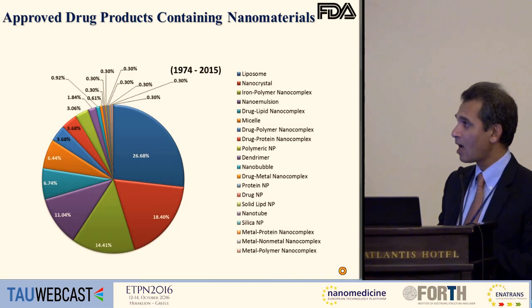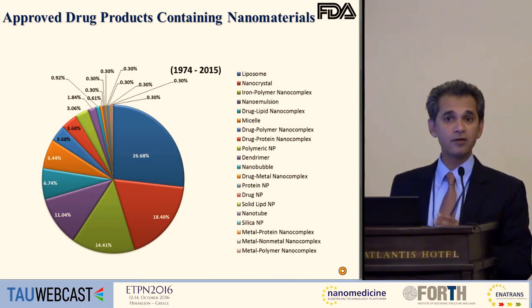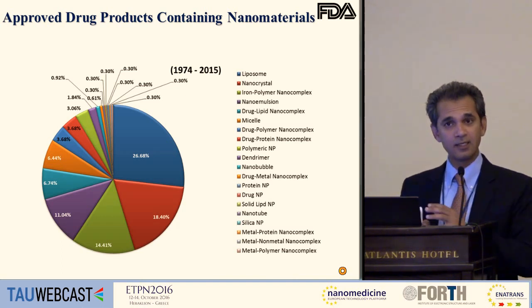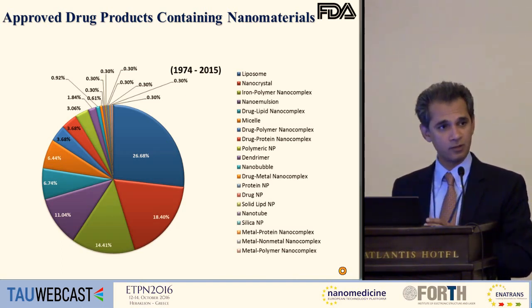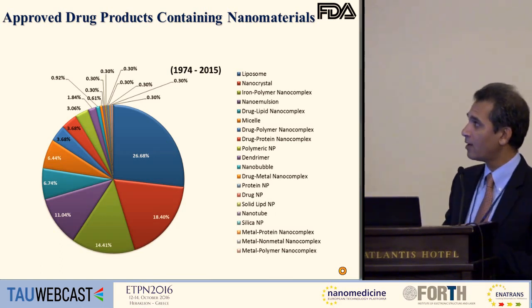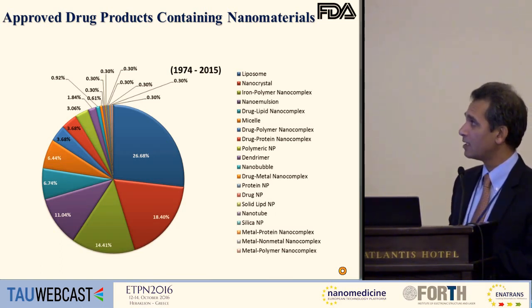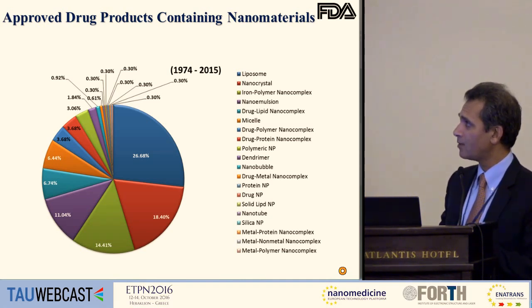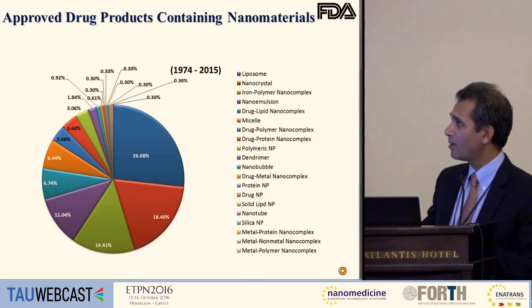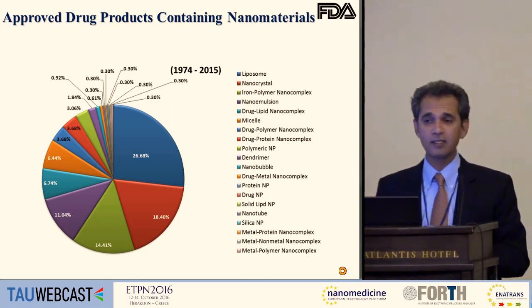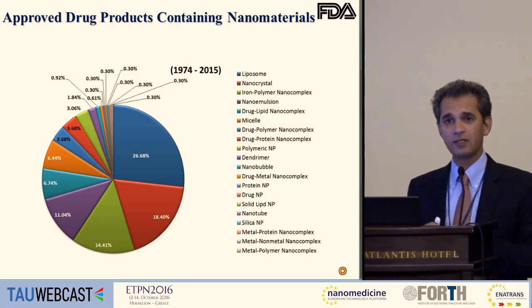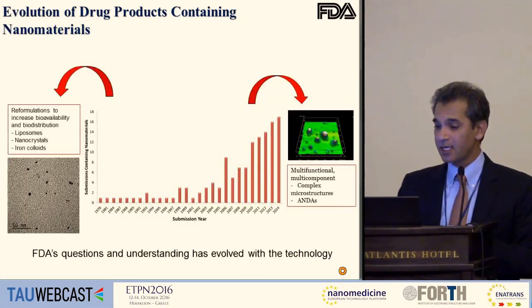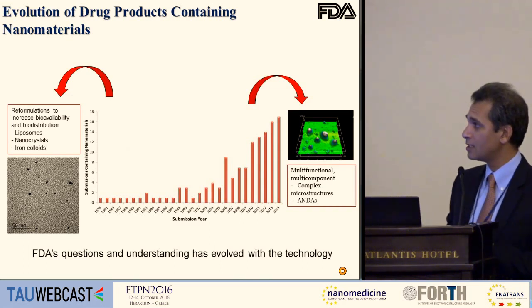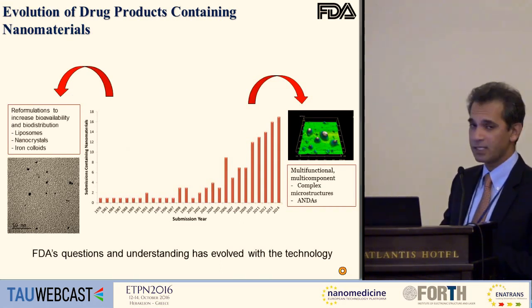So you can see that almost 1/4 of these, more than 300 or so approved products, these are not in clinic, in the sense they are approved for human use or animal use. And 1/4 of them are liposome based. We have nanocrystals, iron polymer complexes. These are all the different percentages, but drug, lipid, micelles, polymer complexes, polymeric nanoparticles, and so on. But if you look at the metallic components, these are really a tiny portion of these submissions, metallic or metal oxide containing.